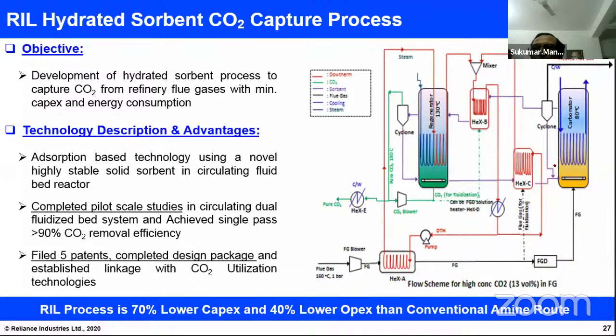we take it out from here at the top, and then it is getting heated up. The heat transfer, the network exchange concept, the heat pump concept is utilized so that the solvent is getting heated up. And here on the left side is called the regenerator, where CO2 and solvent are getting regenerated at 130 degrees centigrade, and CO2 comes out. That CO2 is used again as a fluidized medium to take the CO2 out, and you are getting pure CO2.